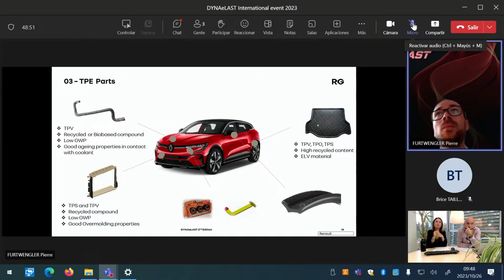For the carpet, we are pushing a lot for the recycled material, especially the end-of-life vehicle recycled material. And one thing which is quite challenging for this carpet, even if it seems very easy because you just put your feet or your luggage on it, is that we have to be sure that there is low odor emission, because you don't want to have an odor of plastic in your car, and with recycled material, sometimes it's quite a challenge. So here was the overview of the main TPE parts we can use. There are plenty of others, of course, but we cannot go through all of them.